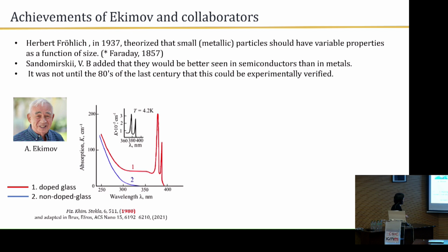Ekimov was working on doped glasses, color glasses, which are vitreous matrices that can be doped by the inclusion of several substances to make them colored. What he observed upon mixing several components in his glasses is that the absorption spectrum, as you can see here marked with number 2, of a non-doped glass was completely different to the absorption spectrum of the glass doped with a compound containing copper and chloride. So he immediately realized that inside this glass he had cuprous chloride, or copper chloride 1, which is exactly the absorption spectrum that you can find here for the bulk material.